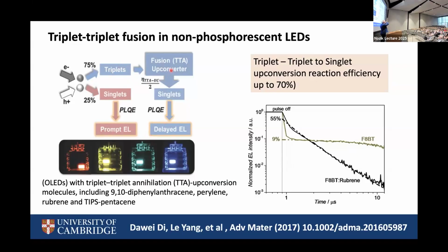The plot on the right just shows what happens when you switch the diode off. There's a sharp drop as you've lost the singlets, and then a slow decay following a bimolecular kinetic as the fusion of triplets runs its course, and you see emission coming out of it. It's not perfect. The efficiency of the blue pixel in OLED is pretty rubbish, and it would be lovely to get a better solution to it.